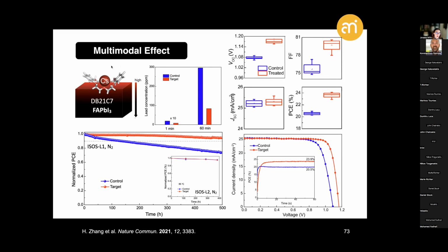Now, in this case, apart from the beneficial photovoltaic effect and the stabilization of the resulting material that I would like to especially highlight, it is important to note that these systems illustrate a certain potential for increasing the sustainability of these materials, as when these solar cells are immersed in water, we see a substantial reduction in the release of lead ions, suggesting that some of such strategies could be used in reducing their negative environmental impact.